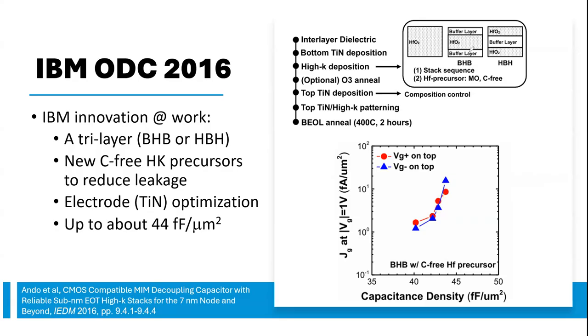It's a tri-layer. And for the tri-layer, they have 2 approaches. One is a buffer layer, top and bottom, and you sandwich high-K in between. High-K, I mean hafnium oxide. Or hafnium oxide top and bottom with a buffer layer, something, in between. He didn't tell. But later we find out what it is, right? So this is how he achieved 0.8 nanometer EOT. Of course, with some good high-K material.